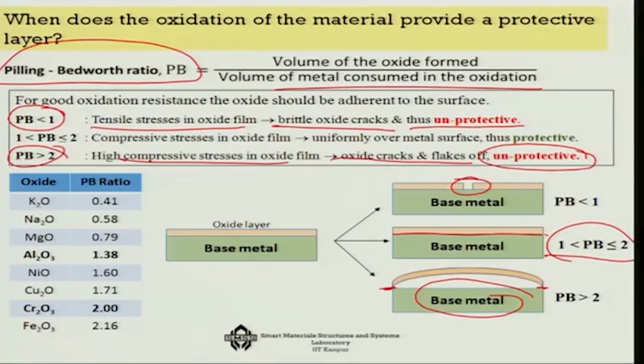So, for example, if you use potassium as a layer, potassium oxide would form, but the PB ratio is much less than unity. So, that means that there will be brittle oxide cracks and potassium cannot be used as a layer. If you use sodium, 0.58, the same problem, okay, there will be crack due to tensile stress. Magnesium oxide, again a similar problem, but aluminum oxide, it is between 1 and 2. So, it will very nicely work like a protective coating.